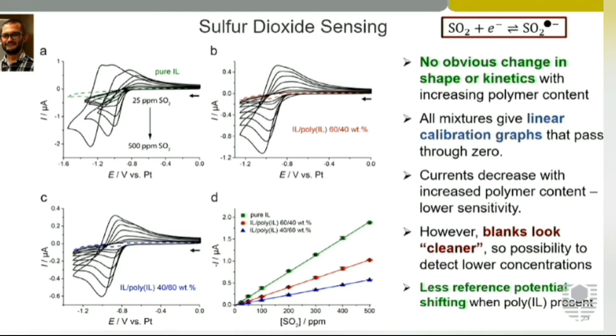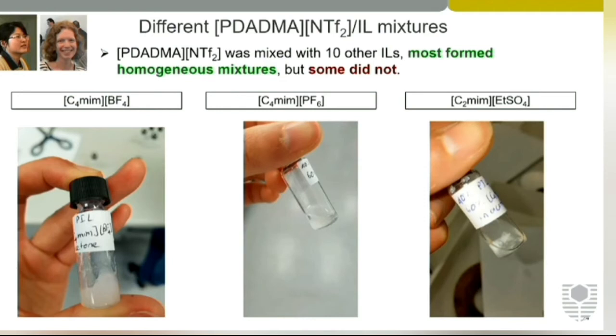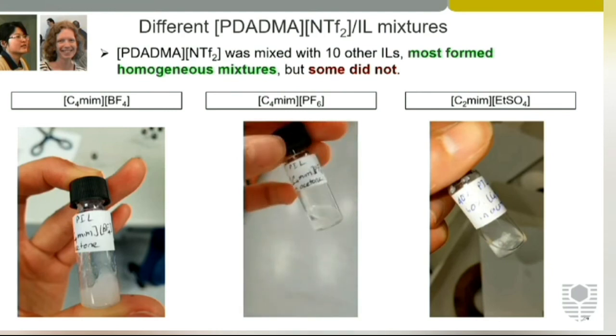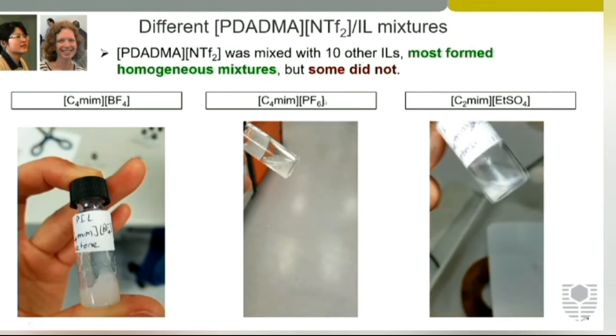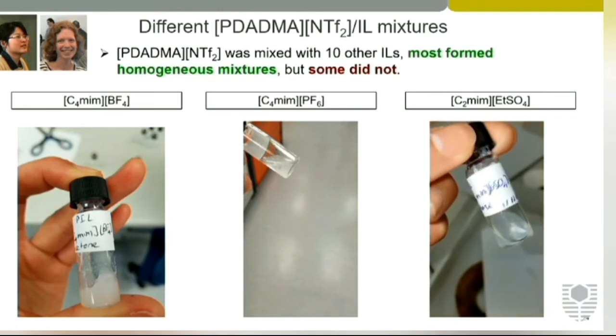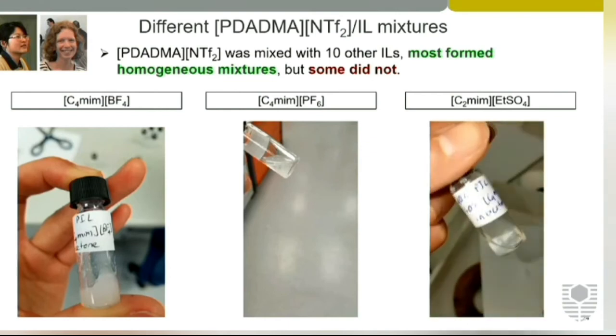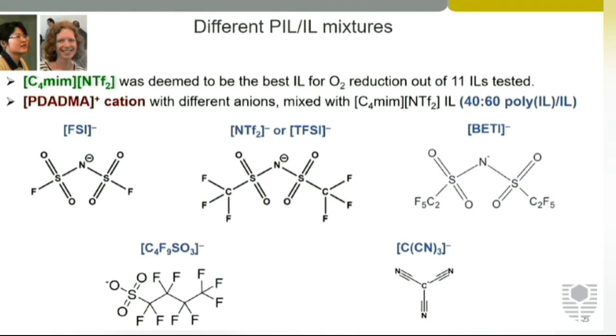So we're still doing quite a lot of work on this, and we're also trying to commercialise this in the next couple of years. So we're also trying different polyionic liquid mixtures, because obviously I mentioned before there's a whole range of anions and cations. Some of the ones we tried do not form a homogeneous mixture. You can see the polymer and the ionic liquid phase is separated, and also in this case here. And this happened with the ionic liquids which had these kind of more different chemical structures and more hydrophilic type ions. But out of 11 ionic liquids tested, the C4-MIM NTF2 was the best, and we have been now using this ionic liquid to then look at the effect of changing the structure of the polyionic liquid's ion.